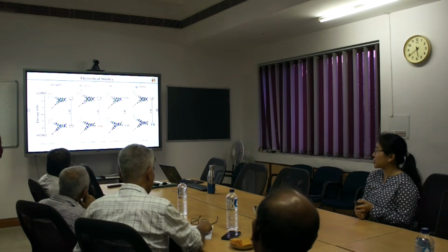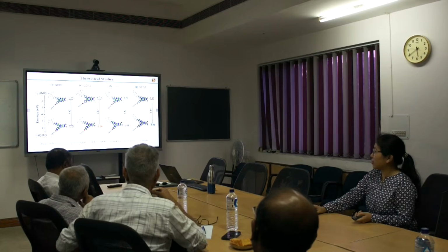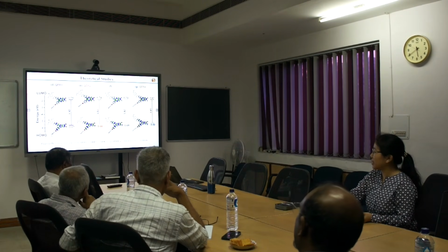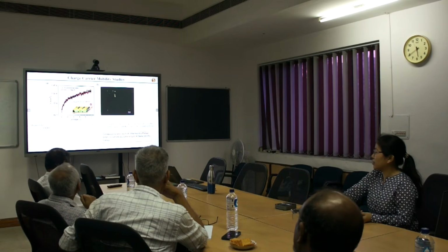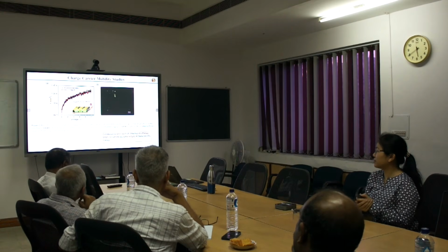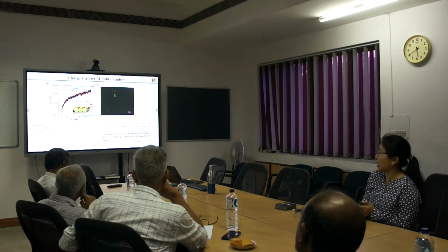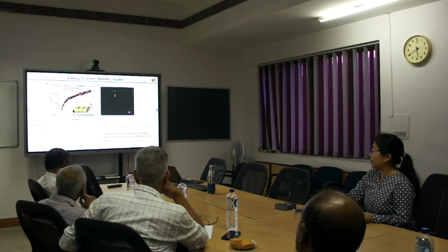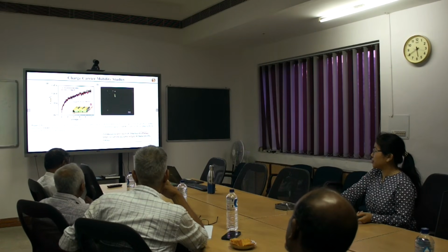All the molecules showed aggregation-induced emission, and one molecule, QPR1, showed liquid crystalline behavior. The liquid crystalline compound had a theoretical HOMO value of minus 5.67 electron volt. So this was studied further using the SCLC method, where the hole mobility of the material was analyzed. For this method, the ITO, the indium tin oxide, is used as the anode, and the compound was sandwiched between the anode, that is the ITO, and the electrode, that is gold.